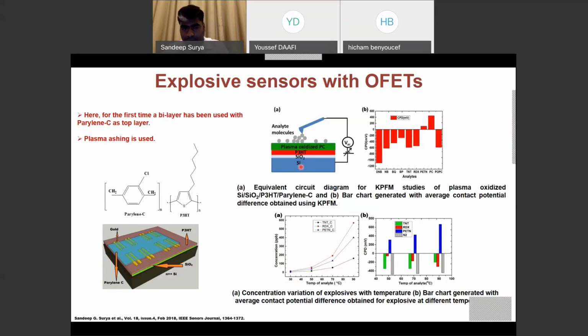On the go, this is what we realized. We have the same stack that we used for the OFET, but on the top we have here plasma oxidized parylene. In the case of Kelvin probe force microscopy, we have the AFM cantilever tip that is doing the scan over the surface, recording the surface potentials. On the right, what you see here is the measurements that were done with the AFM tip, KPFM tip. The first and foremost being the PC, which is parylene. We saw the surface potential coming around 400 millivolts, that is in the positive domain. The moment you do the plasma oxidation, as I've told you, it starts opening multiple dangling bonds of COO, C double bond O, C double bond C, because of which the contact potential difference or the surface potential tends to go towards negative, and it becomes around 600 millivolts kind of. This is the active material for our further studies, plasma oxidized parylene, which is called POPC.